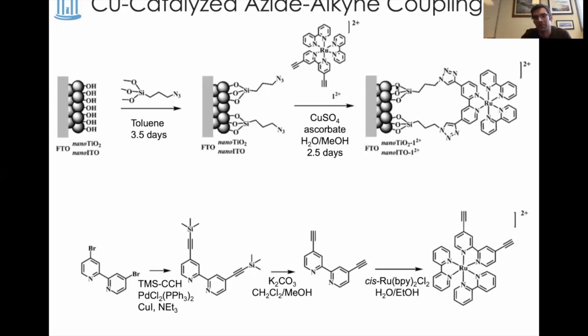So now you have a strong linkage to the surface, a covalent linkage to your catalyst, and a controlled reaction. So this is representative of, I think, all of the examples in this part of the talk: we don't just need to do surface functionalization chemistry, installing azide groups. We also need to do what we did in the first part and functionalize the catalyst as well. But in this case, it's a functional group that would not attach to a surface on its own. It's designed to pair with the azide that has been decorated on the surface.